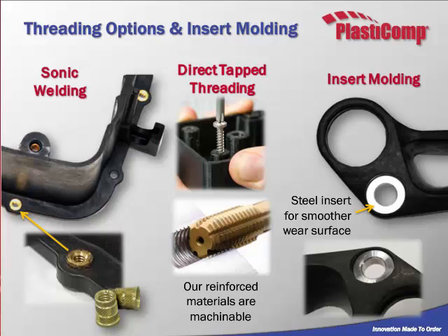I wanted to cover a few threading techniques that we have. This is important in machine design. When it comes to this material, it's stiff enough that you can actually machine into it, and that's good if you want to get some direct threading and you don't want to have to deal with inserts. And the pull-out strengths were quite a bit. Even for glass fiber reinforced materials, we are seeing it ranging from 1,000 to 2,000 pounds of pull-out strength. You also can sonic weld in inserts if you feel more comfortable with that, or if there's a compression load that you're nervous about. So this material lends itself to both direct tapping and sonic welding in inserts.